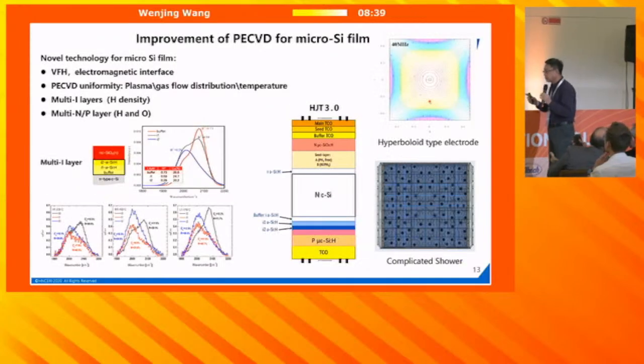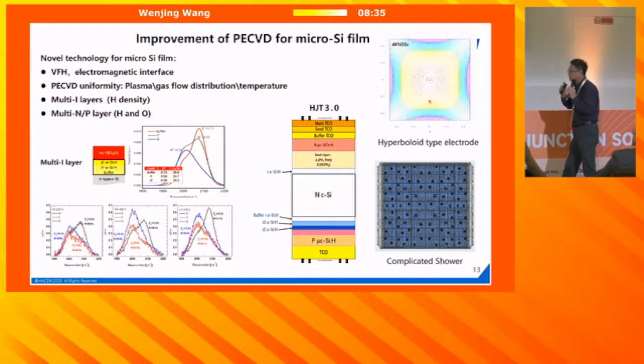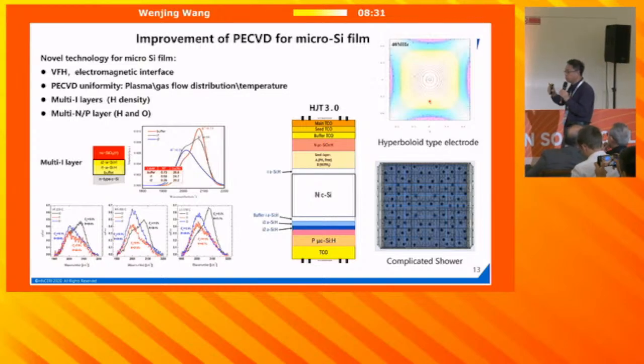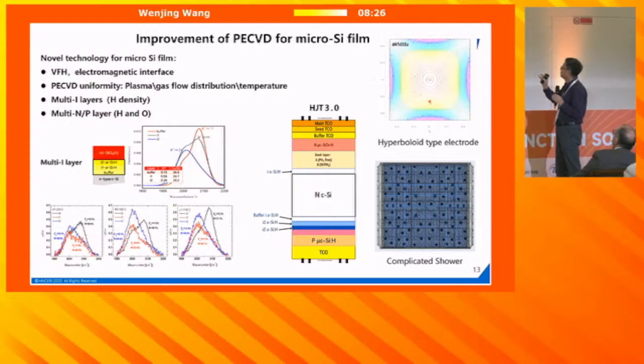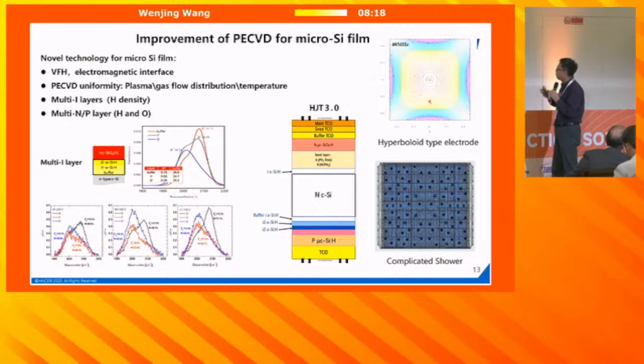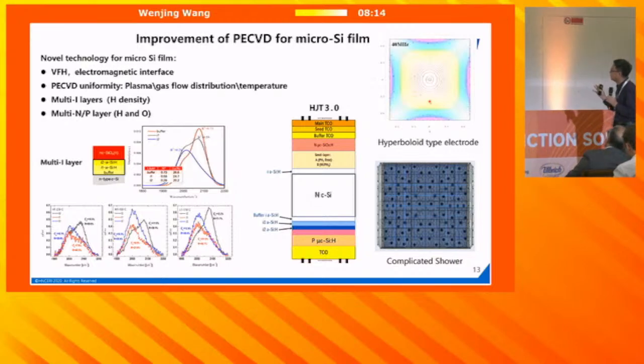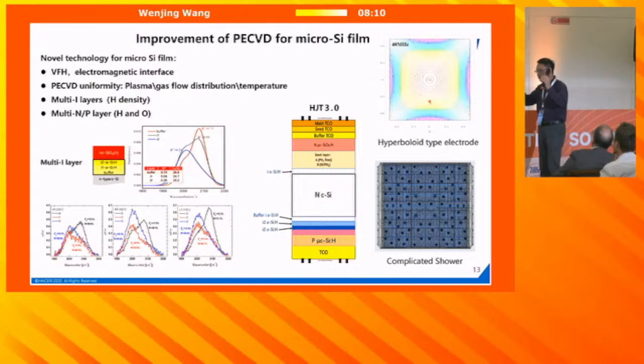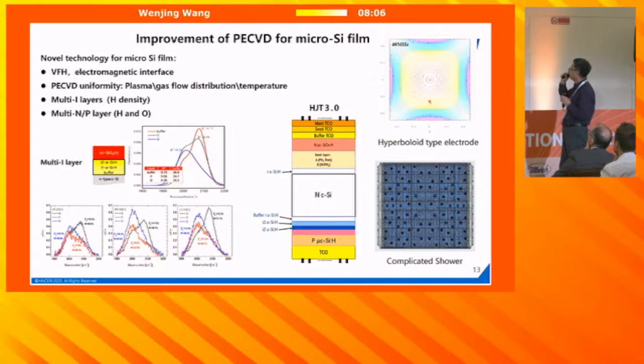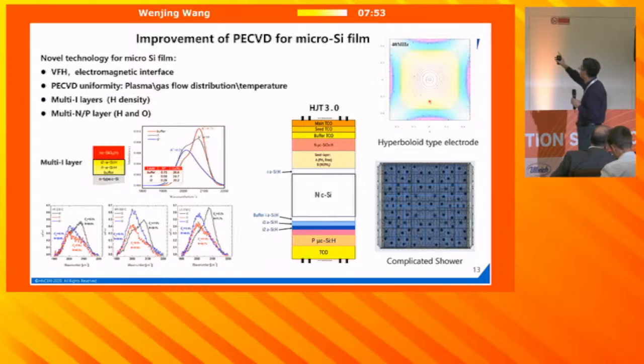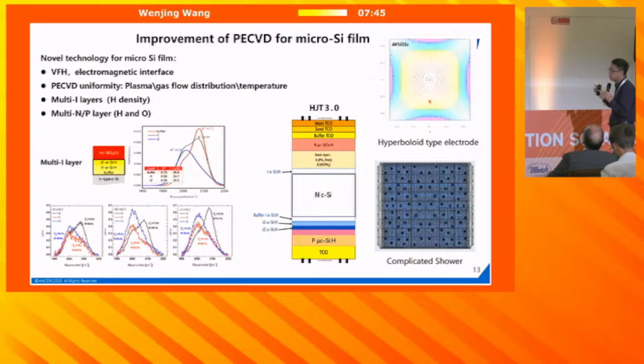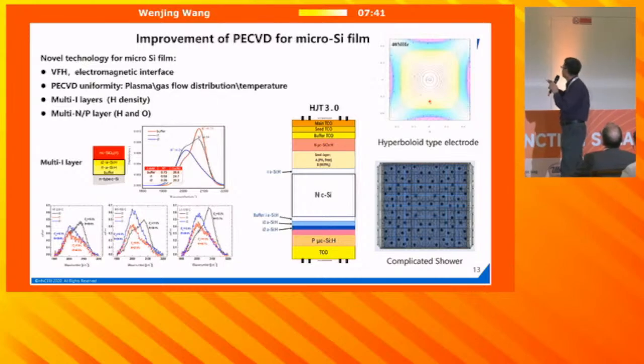For structure in the lab it is not so difficult, but for mass production, making a narrow distribution of the efficiency is quite difficult. We have some novel technology for micro-Si film, such as VHF. So we have to overcome the electromagnetic interference, and for the PECVD system, inside the chamber, we have 3 kinds of uniformity: the plasma uniformity, the gas flow distribution uniformity, and the temperature uniformity for the whole substrate. For plasma, we have to use a hyperboloid-type electrode. It's a kind of curved-surface electrode.